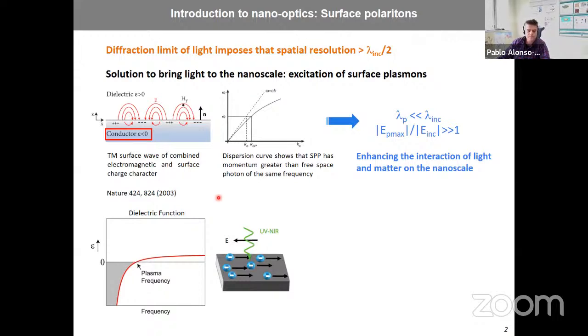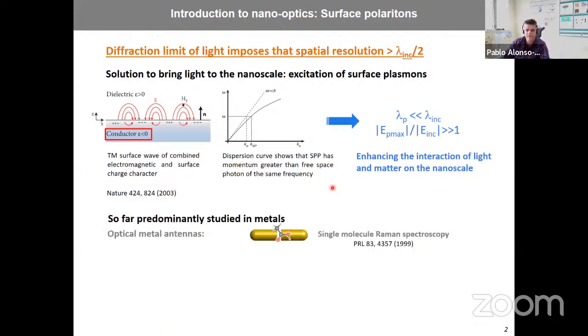This has been studied for years in metals, right? And this is because this material with negative permittivity is well fulfilled with metals below the plasma frequency. One can think of it like when one illuminates a metal, the free carriers in the metal, because they have a negative permittivity, try to screen out this incident field. They screen it out by moving in such a way that they create dipoles that cancel the incident field, right? So this has been studied for years, and there are key results in this field, like single molecule Raman spectroscopy using optical metal nanoantennas, where localized plasmons are excited in very, very small volumes. It's like a nano lantern, where you can illuminate only one molecule, and therefore you can have this signal, right?